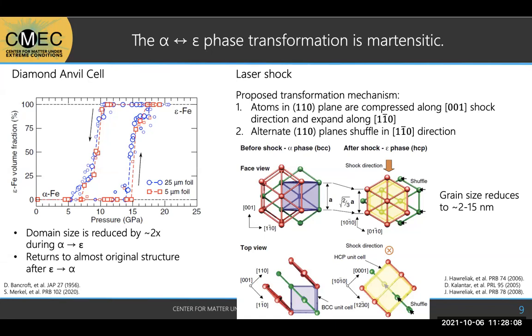But then secondly, what happens is those atoms in that green plane actually shift. So they shuffle a little bit. And they essentially find that shuffling brings them to a lower energy state. And so it's more favorable for them. And so that's how you end up with this hexagonal structure.